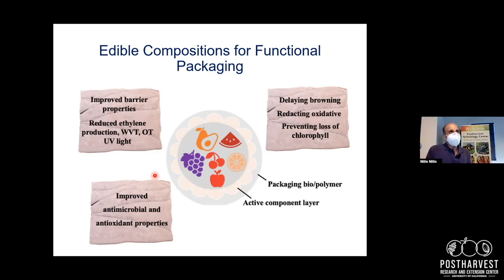But from what I know, some of the studies that we have done and probably more others have done, what we find is definitely using some of the edible materials, you can suppress the water loss from the produce, and that could lead to extending the shelf life significantly. You can also suppress the oxygen permeation, and that makes a big difference in terms of extending the shelf life there. So as I understand, one of the things that the product Apeel offers is the barrier against water loss, which is one of the biggest variables that they control. The other variable is the oxygen barrier properties in this case.